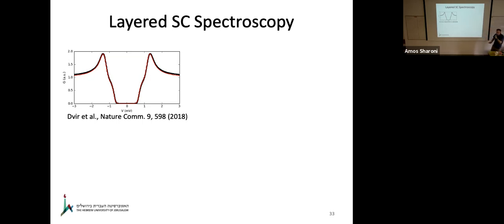That's important. Shira? Okay. On which scale will they engage? You saw them, these are atoms. What, laterally? Several hundreds of nanometers, as big as we can see. This is a TEM image, so as large as your TEM image, it engages well. Of course, when you go to hundreds of nanometers, you start to see bubbles and dirt and stuff like that. We can see them in the AFM with the bubble. We can see the TEM at the tens of nanometers. Somewhere in between, you don't have a perfect micron by micron. It's not micron by micron. What is it? 100 nanometers.